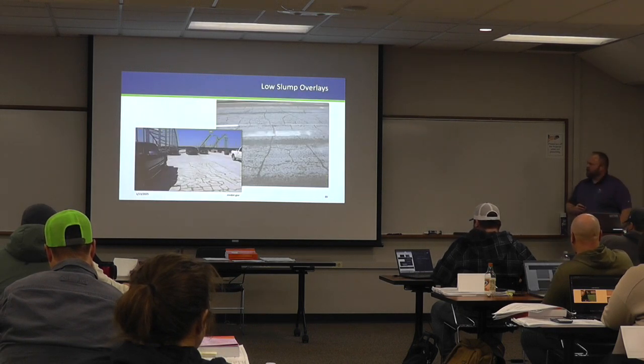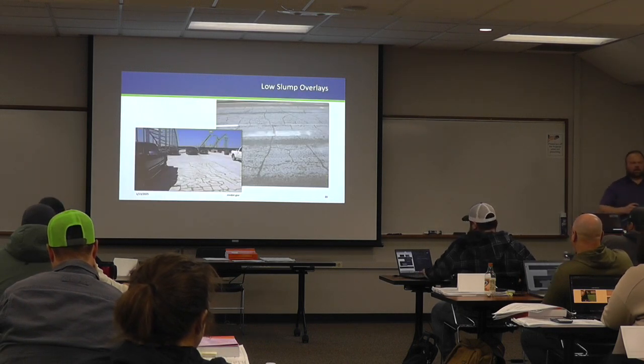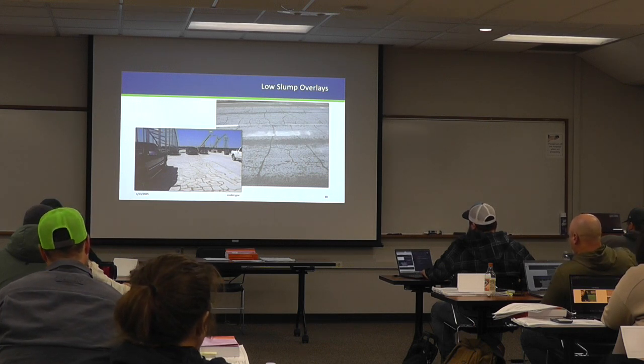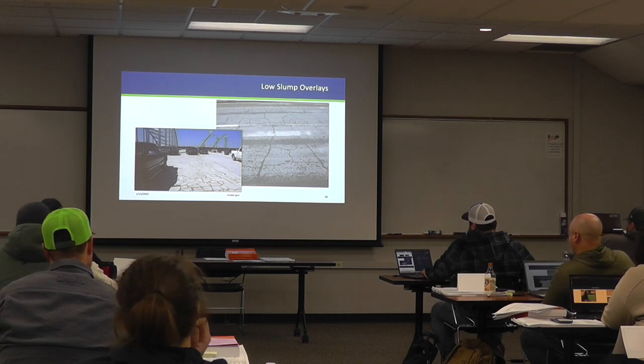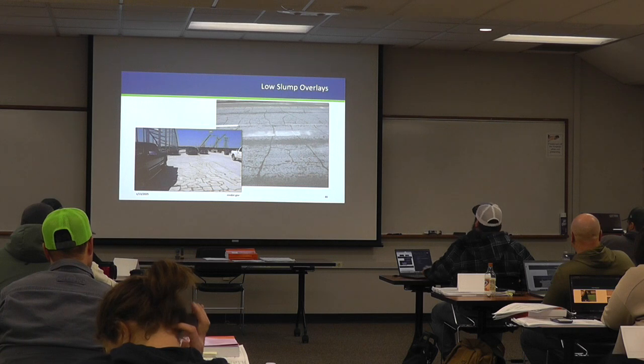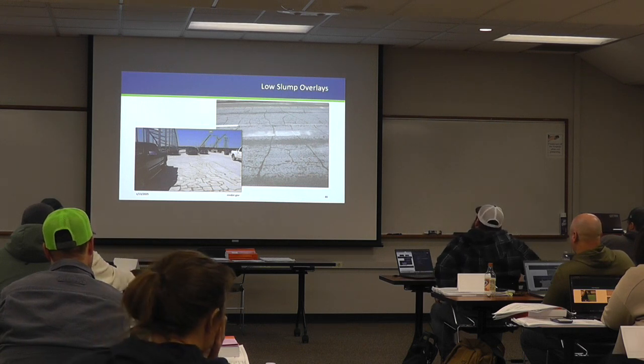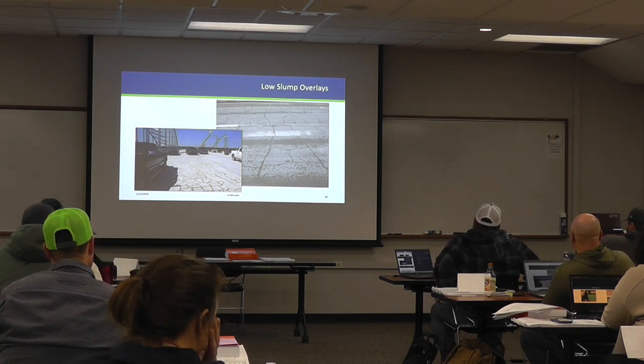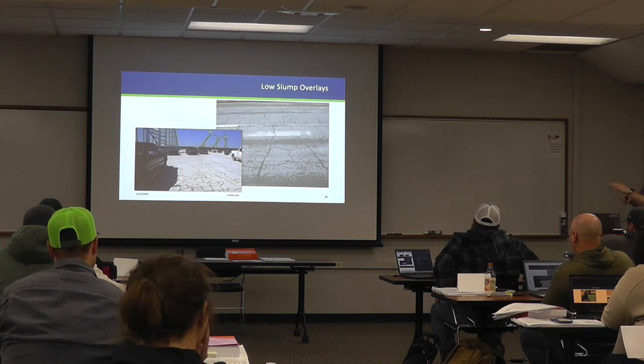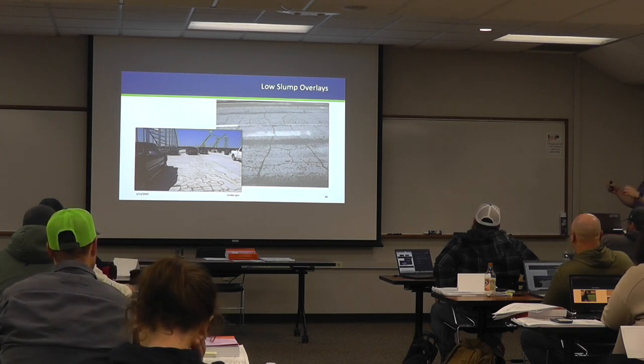Now, our low slump overlays, this is what they can tend to look like. One of the reasons why, at least in my opinion, is that this is a mix design that has 836 pounds of cement in it and hasn't changed since the 70s. But the cement grind has gotten finer over those few decades, and the finer the grind is, the faster the concrete is going to gain strength. So over 30 or 40 years, with that concrete not changing but the grind changing, we're getting faster setting concrete, and shrinkage is happening quicker.